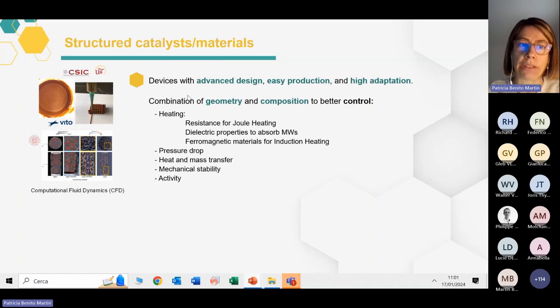We are preparing the materials by 3D printing, guided by computational fluid dynamics, to have devices with an advanced design, easy production, and high adaptation. The key that we are trying to achieve is to combine geometrical parameters and composition to, first of all, have the right heating, so Joule resistance, the dielectric properties or ferromagnetic properties, but also combining with low pressure drop and a mechanical stability that is very important because we are generating a solid inside the reactor, and also heat and mass transfer. And all of these parameters will determine the activity.